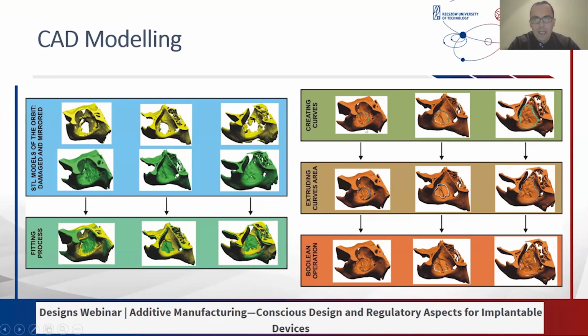First, we create curves representing the defect area. This defect area we cut on the model that is not defected, not damaged. So we first create curves that create a closed area. Where we have a closed area, we extrude it, and then using a boolean operation, we create a cut on the final model. So we create one model representing the undamaged side, and on this model we have the cut area of damage.